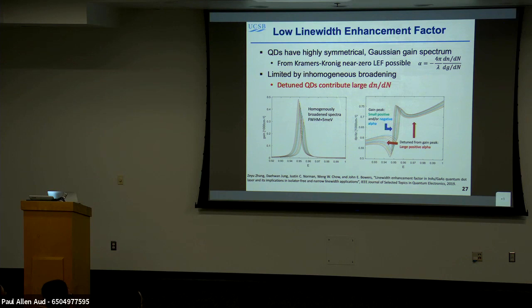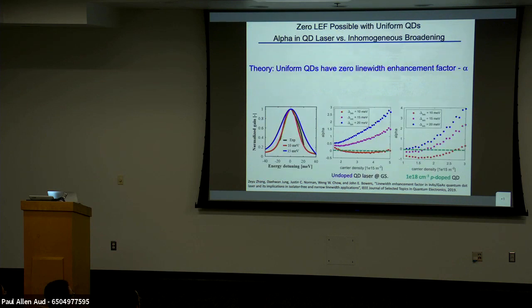And what happens is on each side of that 0, you get large contributions to the phase terms in here. So out here you get large positive alpha, and in here you get negative alpha. And so what you have to do is shrink this up. And you can see this here. These again are, the black is our data on the improved devices when we work hard to make dots very uniform. And the blue and the red are Weng Chow's calculations. So if you go from this 50 meV photoluminescence line width down to 10, it has a big impact on alpha. This is 20 meV, this is 15, this is 10 meV. So down here, alpha is 0.